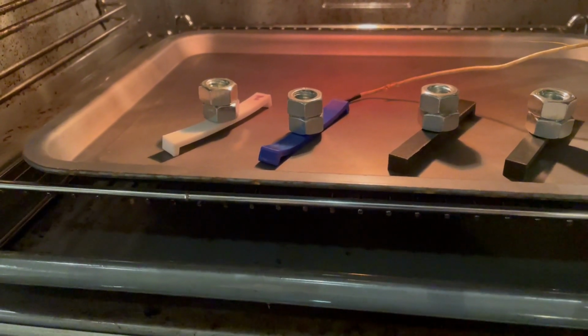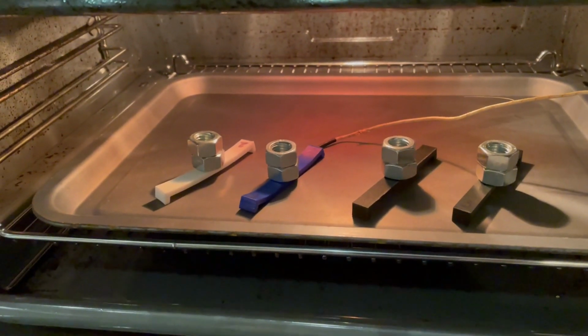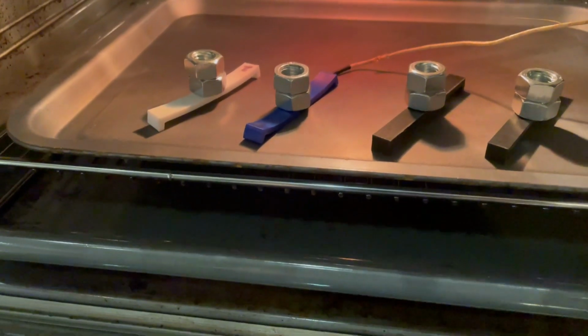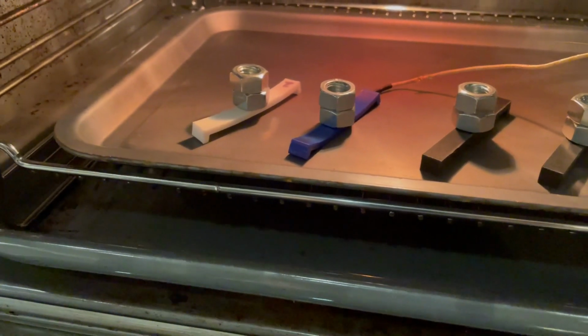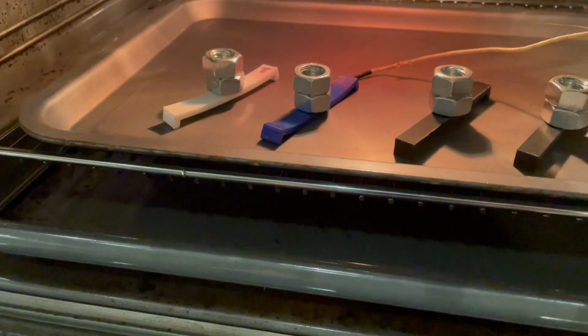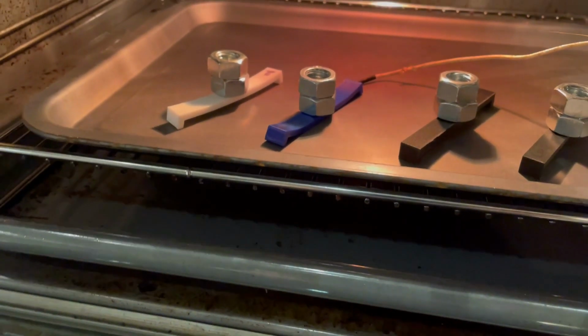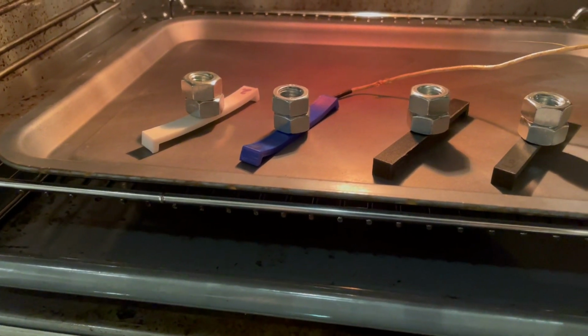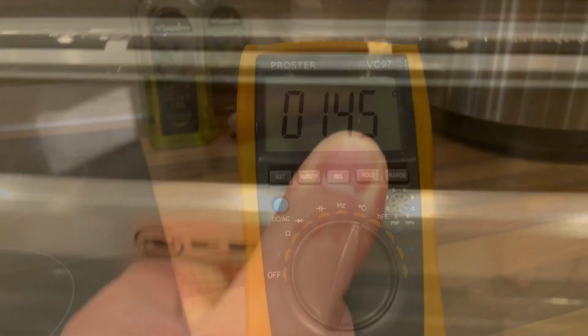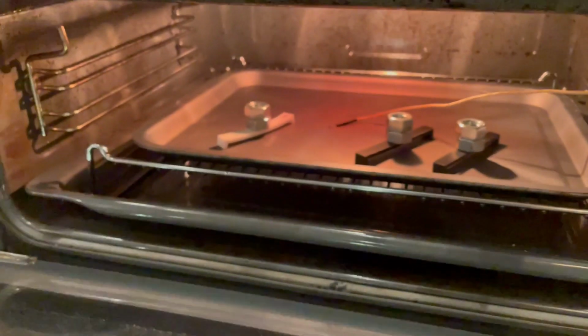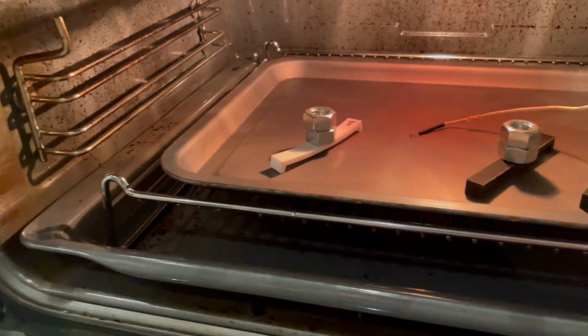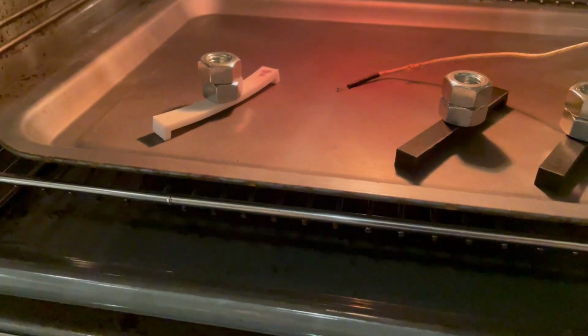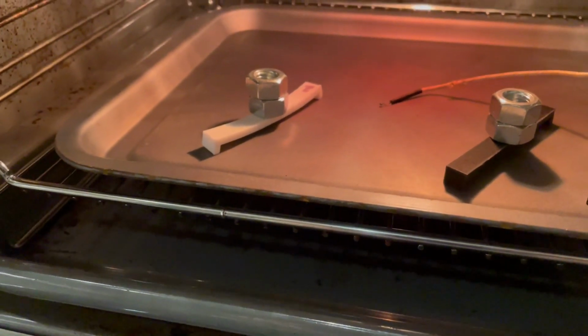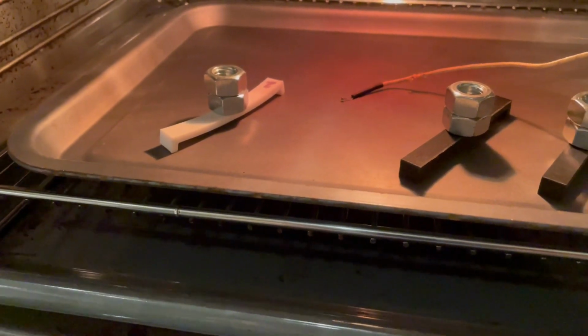At nearly 90 degrees, the PETG has gone. So the annealing giving that a 10-degree improvement. The PLA, however, is going strong, has not shown any signs of buckling at the moment. So we continue the test. Okay, so 145 degrees and the PLA is starting to show some signs now. It is starting to buckle significantly. Far better than the 60 degrees it managed beforehand.